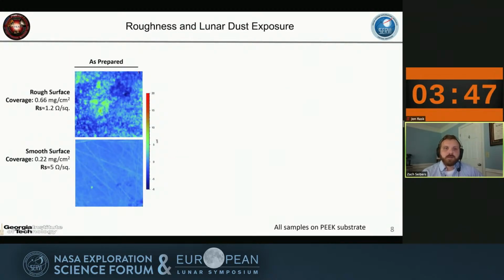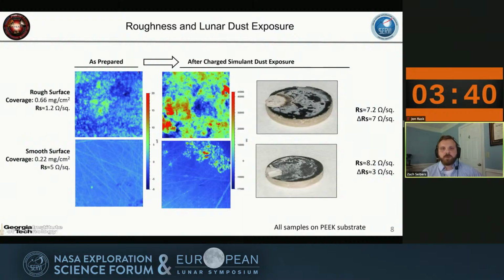Very quickly, here are the profilometry scans that I showed you previously, two of the samples. If we expose those samples to charged simulant dust, we can quickly see that there's a big difference between the amount of dust on the surface and the starting roughness of the laminate layer. Not only is this readily apparent in the profilometry scans, and I apologize for the difference in units here between nanometers and microns, but the red and blue are still orders of magnitude high and low, so the pictures are still somewhat descriptive. We can also see it optically. When we look at the intensity of the grayish white color here, that's the dust that's stuck to the surface, even after it's been removed from the vacuum chamber. The gray is much more intense on the rough surface rather than the smooth.